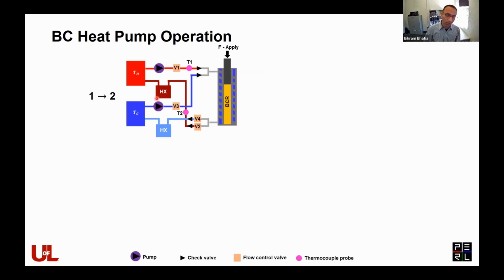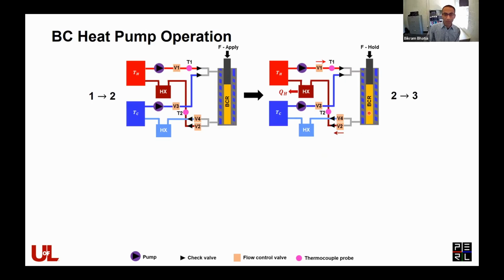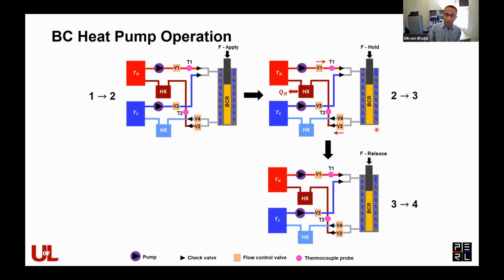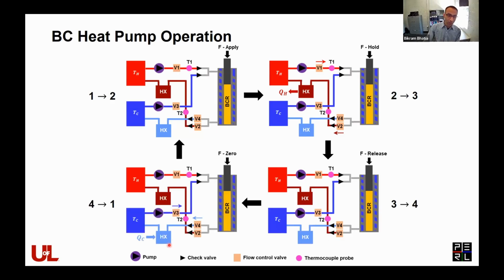So the way this heat pump prototype works is you first compress the barocaloric material while all the valves are closed. There's no heat transfer media flowing through the core. You apply pressure, the temperature rises. You open the valves and allow the temperature of the heat transfer media to rise as it passes through the barocaloric core. And that heat is rejected through this heat exchanger and is returned to the hot thermal reservoir. We then close the valves and we release the pressure that causes the temperature of the barocaloric medium to drop. We open these other valves from and to the cold thermal reservoir and allow heat exchange to the cold side thermal reservoir and basically release the pressure and repeat the cycle again.